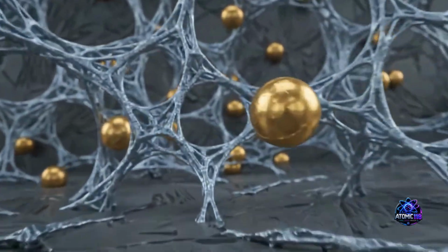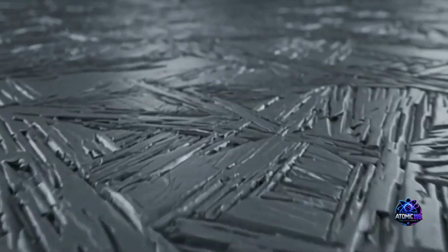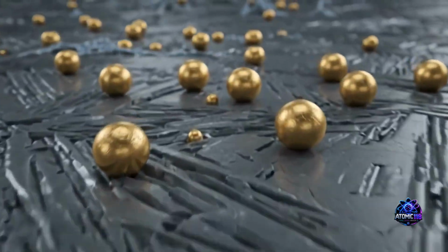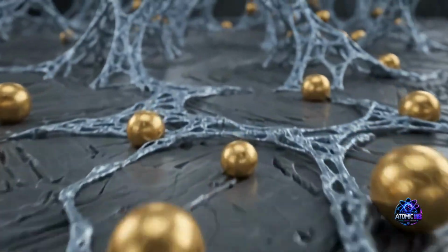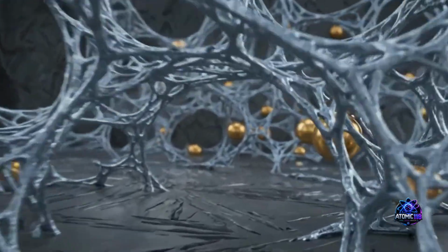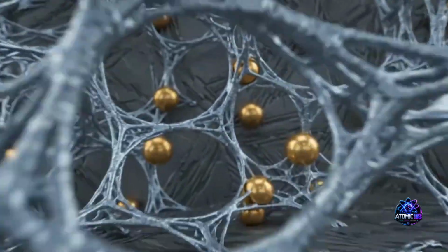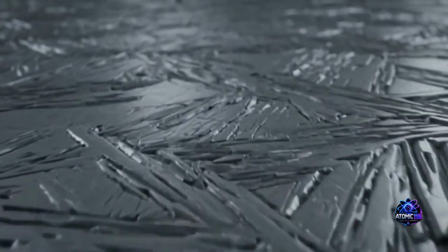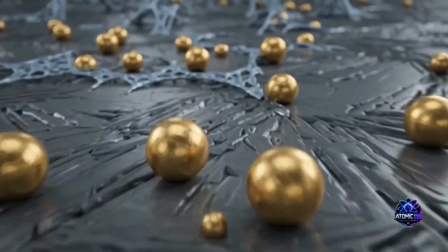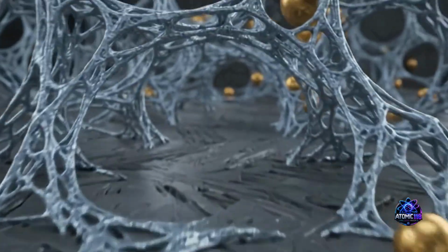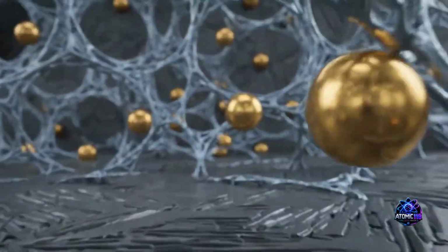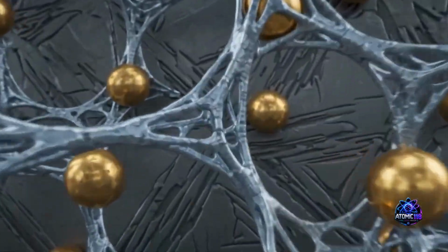So molybdenum atoms reach out, overlap perfectly, and lock together with a grip so tight it takes massive amounts of thermal energy to break them apart. It's like a person with long arms giving a perfect, unbreakable handshake. That is a great way to put it, which is why pure molybdenum has a melting point of 2,610 degrees Celsius. Wow. Yeah, the atomic handshake is fundamentally unbreakable under normal thermal conditions.